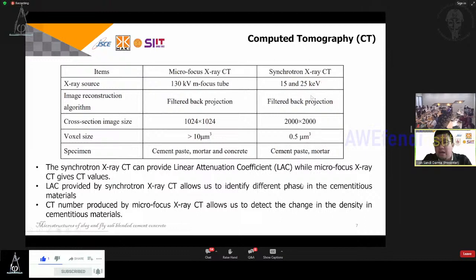With both CT and LAC, we could make a good relationship between the CT number or LAC and the phase of a microstructure itself. As I explained before, LAC provided by synchrotron X-ray CT allows us to identify different phases in cementitious material. It's very easy compared to XRD. And the CT number produced by microfocus X-ray CT allows us to detect the change in the density in the cementitious material.